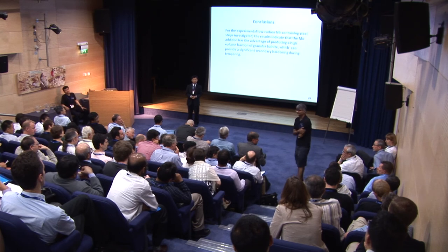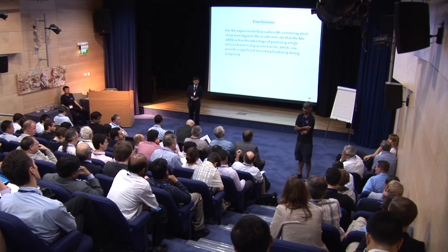I'd like to confirm that we've also measured molybdenum in a number of niobium carbides. Your presentation showed very clearly that you have secondary hardening at 600 degrees, and I guess that's probably the peak of the hardening. My question is, what about strengthening carbide formation in the bainitic microstructure itself? It's obviously incomplete because you can increase the strength by a secondary heat treatment. But can you tell us anything about the extent of precipitation during or after the bainitic transformation itself in the primary cooling stage?